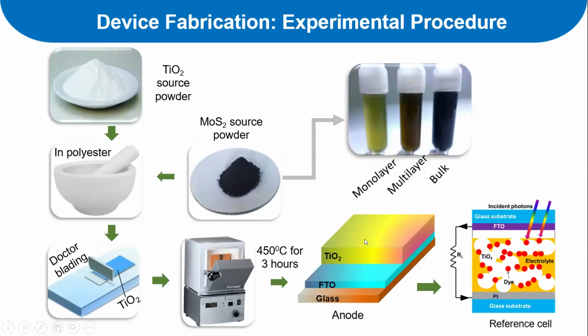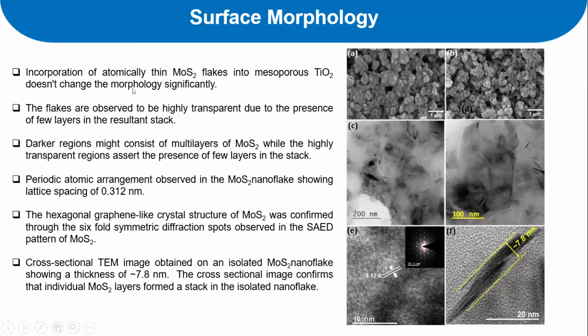So that is a major idea. If we can have that one, the organic dye molecules have the property of narrowband absorption that can be solved by introducing the 2D layered semiconductor, because they have optical band gaps which are variable in different ranges. So that is the idea. Once we have that, we can coat the 2D layered semiconductor onto the electron acceptor, titanium dioxide. In this particular case, I have coated 2D layered moly sulfide on top of titanium dioxide.